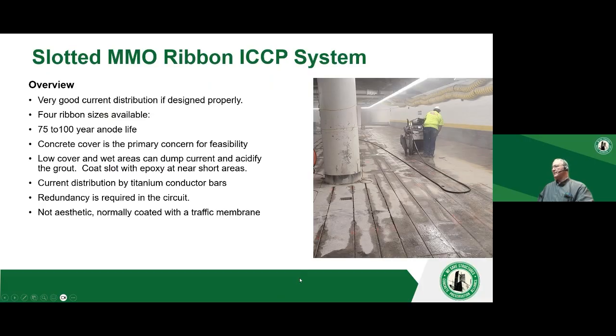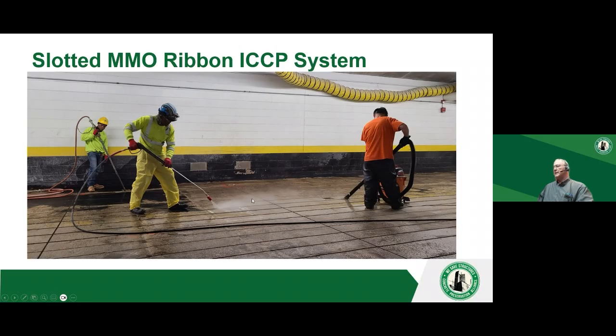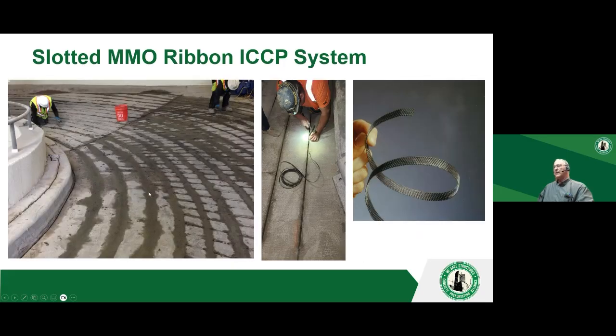Then we have ribbon systems. This is a system where we cut a slot, and these slots are typically a foot apart. They could be 18 inches, depending on how much reinforcement you have and the size anode. The key for selecting this is make sure you have enough cover. You need enough concrete cover to cut these slots. The slots are cleaned, then they are grouted, okay? And in this case here, there's a parking ramp, and you have a current distributor bar going perpendicular.